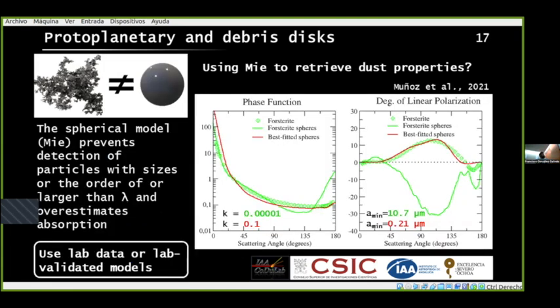In fact, we've done this in the lab. We measure the curves of polarization and phase function curves of forsterites. We have calculated the Mie model, the Mie curves for spherical particles with the same optical parameters. You see that they have nothing to do with each other. You have mostly negative polarization in the case of spheres.